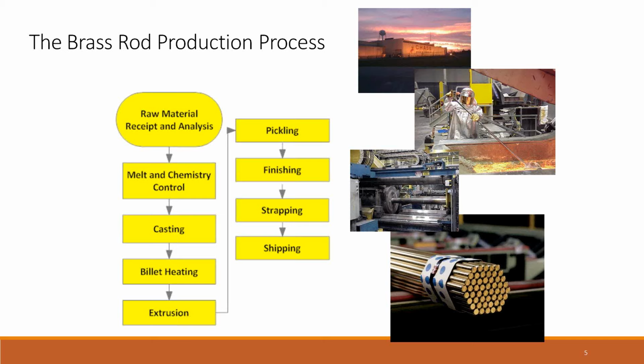The traditional leaded brasses have lead in them that helps with the machinability, but if you don't cold draw it and get that hardness up, as we'll see here in a little bit, you just end up with very gummy material that doesn't break up into small chips and give you the most machining efficiency possible.